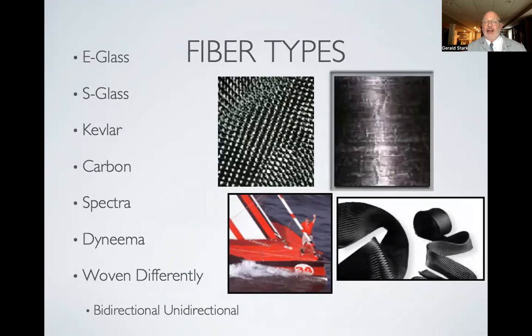Some of the fiber types we have are E-glass, S-glass, Kevlar, carbon, Spectra, Dyneema, and these can be woven differently. The weave of the composite tells you more about what's happening. With most prosthetic feet, it's unidirectional, most of the fibers are in one direction, 90%, and then maybe 10% are just holding them in position. When you see a prosthetic foot with a weave on top of it, it's usually just a cosmetic addition, so that it looks like a carbon weave, but most of that prosthetic blade is actually unidirectional fibers of carbon.